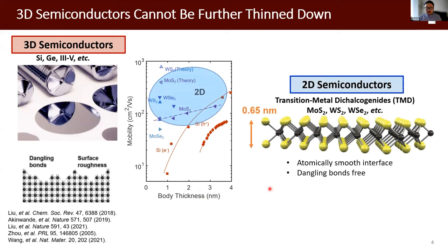Then we introduce low-dimensional materials like 2D semiconducting transition metal dichalcogenides. A monolayer of these materials is less than 1 nanometer. Because of the low dimensionality, they have atomically smooth interfaces and there are no dangling bonds on the surfaces. As a result, the mobility can stay as high as we scale down the body thickness to even below 1 nanometer.